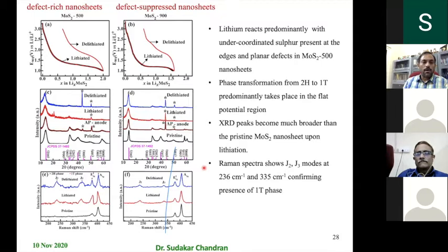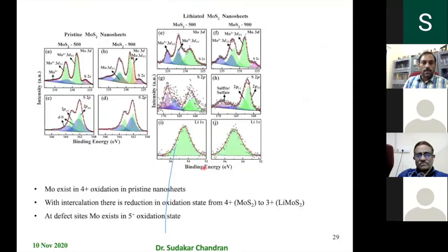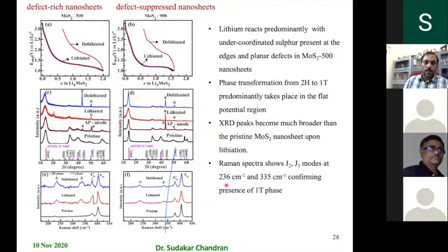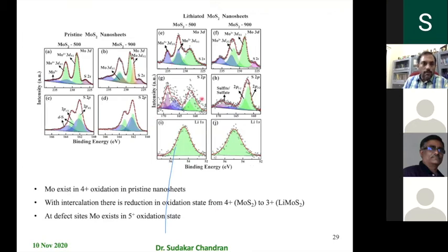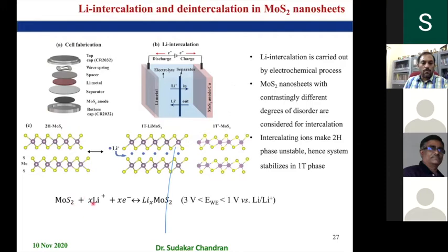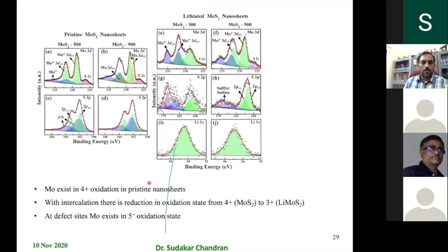So these lithium can go and get decorated on these defect sites, and therefore it would alter the properties. Of course, we did a detailed study using XPS on what happens to the oxidation state and so on. Mostly we see 4+ oxidation state in the pristine form, whereas when lithium is taken, it goes to the 3+ state, and that's what this equation suggests, right? So if you put 1 lithium, the moly in this is in 3+ state, that's what we found. Of course, in some cases you see moly in metal state also because of the reduction we have done.